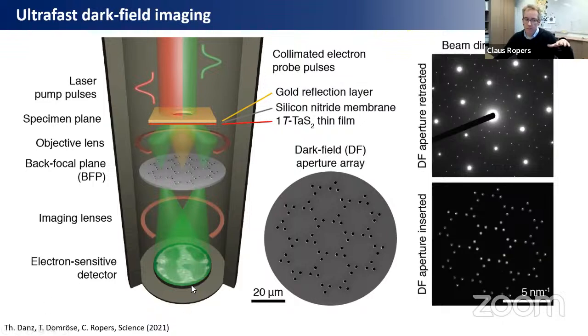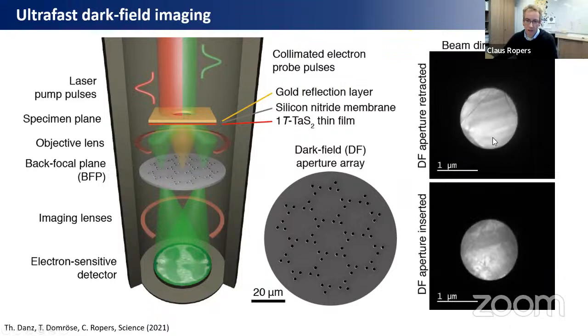The intensity of this image is directly proportional to the square of the amplitude of the lattice distortion. So wherever intensity passes this mask, there's large lattice distortion. Wherever little intensity passes through this mask, there's little lattice distortion. Okay, so this is now two real space images, one without the mask inserted, one with the mask inserted, of about a 1 micron sample. This doesn't look too exciting at first, but you need to realize that the lower image is a direct measure of the lattice distortion and, in essence, of the order parameter of this phase transformation. So it's a new way to get access to structural order parameters of phase transitions.